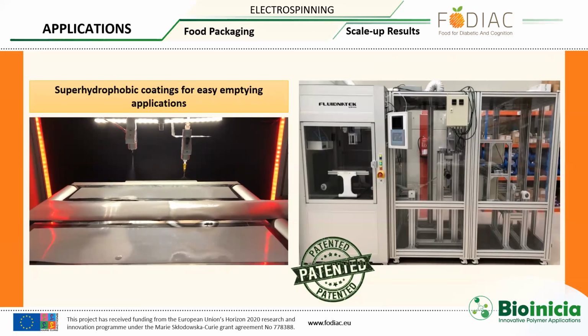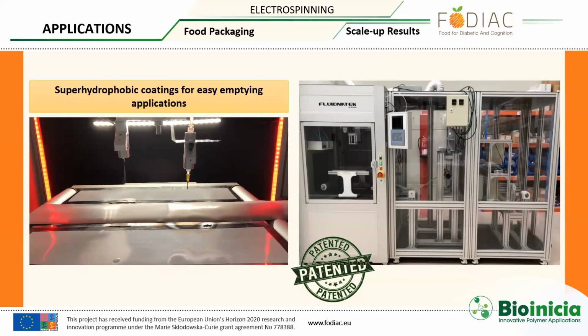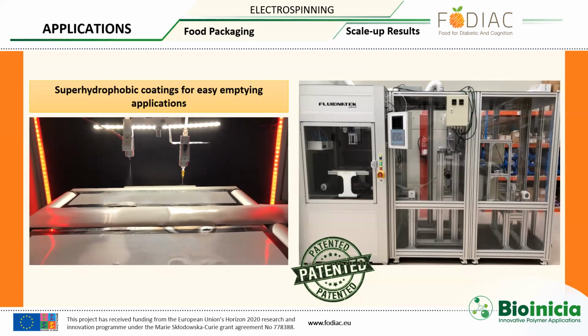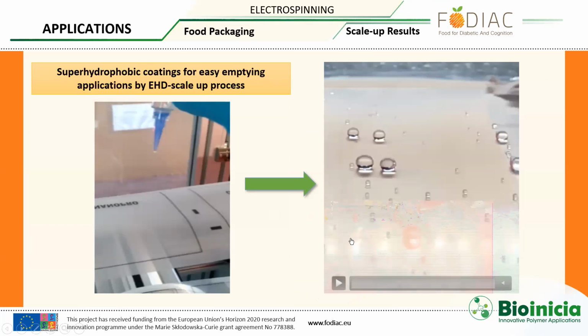This is the very first approach that we did, where we had two injectors and we were electrospinning and electrospraying at the same time. After that, we moved on to the picture on the right, where we built an entire piece of equipment just for this, where the roll goes from the table, where we did the sequential electrospinning and electrospraying, to a thermal lamp, and finally to a roll-to-roll collector. When we reached the end of the roll-to-roll collector, one of the quickest ways to see whether it had worked was to put a few droplets of water onto the material, which in this case I think was low density polyethylene. And we could see that they were clearly super hydrophobic.